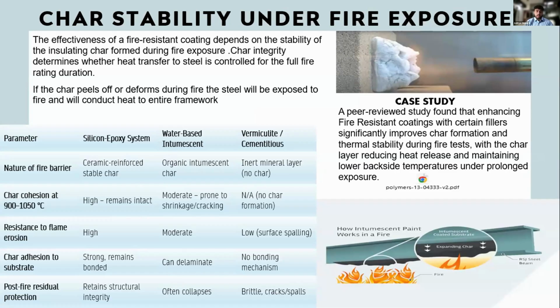So here I have made a comparison of the nature of fire barrier and char cohesion at 900 to 1050. I have attached a case study as well, where it is found that fire resistant coatings with certain different types of fillers can improve the char formation and thermal stability during fire. With the char, they are reducing heat release and maintaining lower backside temperature under prolonged use. Where we notice the silicone epoxy system has a reinforced stable char. As we know, ceramic reinforced stable char means it will stick to the surface no matter what.